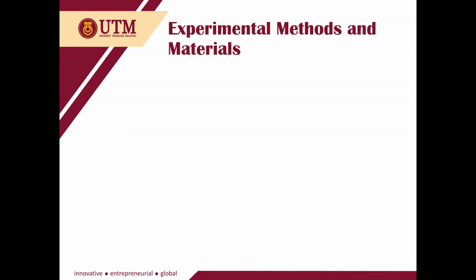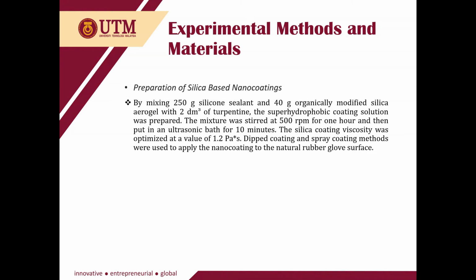For the experimental methods and materials, first, we can move to the preparation of silica based nanocoatings. By mixing 250 gram silicone sealant and 40 gram organically modified silica aerogel with 2 cubic decimeter of turpentine, the super hydrophobic coating solution was prepared. The mixture was stirred at 500 rpm for 1 hour and then put in an ultrasonic bath for 10 minutes. The silica coating viscosity was optimized at the value of 1.2 pascal second. Dip coating and spray coating methods were used to apply the nanocoating to the natural rubber glove surface.